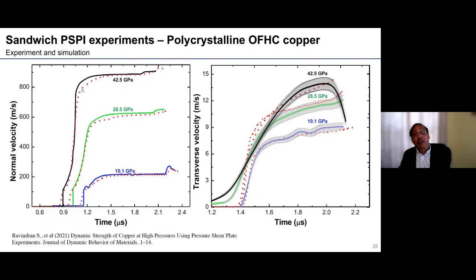So as I mentioned, and this is well known to people who do simulations, the normal response can be fitted with any kind of model for the inelastic response, or the flow strength model. But now the additional information we have is the transverse velocity, and using the constants which I showed you, we are able to fit the model with the transverse velocity much better. So this gives us confidence that we are on the right track.